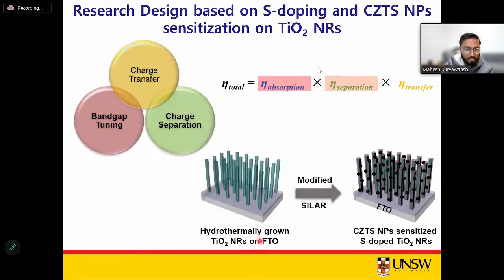So, a little bit about the methods. We have simply grown the TiO2 nanorod arrays using the hydrothermal method on an FTO substrate. And then we have used a modified SILAR method, which I developed during my PhD, for this particular compound, copper, zinc, tin, sulfur. And then we use this method to sensitize these small quantum dots of the CZTS nanoparticles on sulfur-doped TiO2 nanorod arrays.